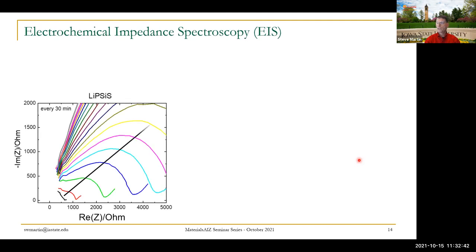We're back to symmetric cells, and I've blown this up quite a bit. This is the pure sulfide. What we would like to have is a very simple arc at very low impedance like this. We don't want to have any impedance across that cell. We want to have a very small impedance, but you see what happens. Every 30 minutes, we just simply take another impedance diagram. We're just sweeping the frequency, measuring the impedance. And if it was perfectly stable and nothing happened, it would stay here, but it doesn't. It grows dramatically. And notice the impedance, 5,000 ohms, very large impedance.